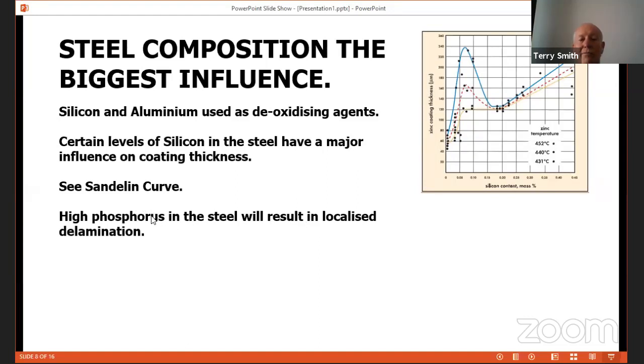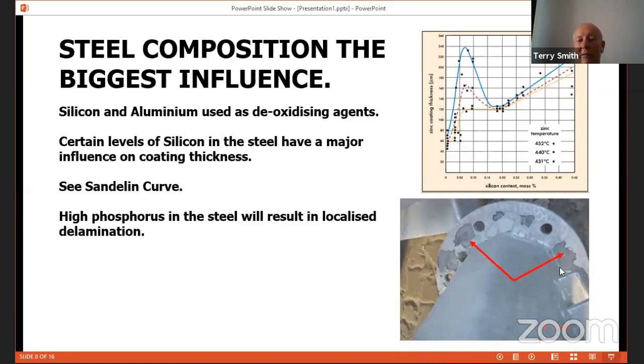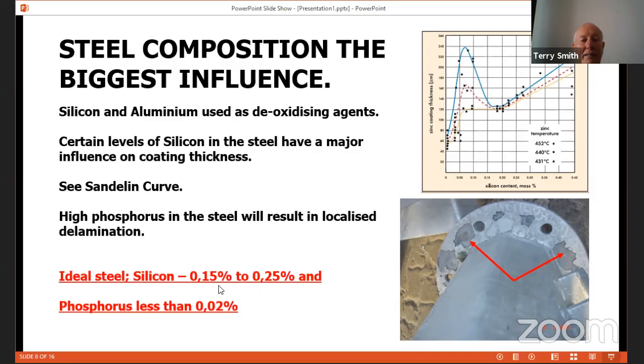Now, phosphorus is not added to any molten steel. It depends on where the steel or the iron is mined in the country or in the world. So you can see this is a mast. The bottom flange has a high phosphorus. You can see the delamination, whereas the mast itself, the galvanizing is 100%. So ideal steel: silicon between 0.15% and 0.25%, and phosphorus less than 0.02%.